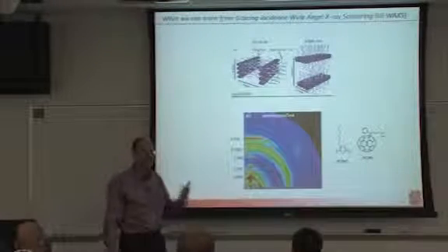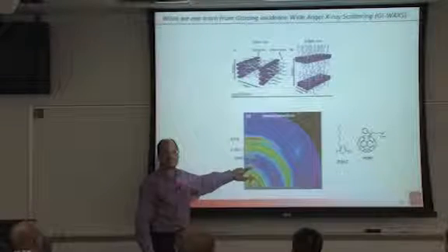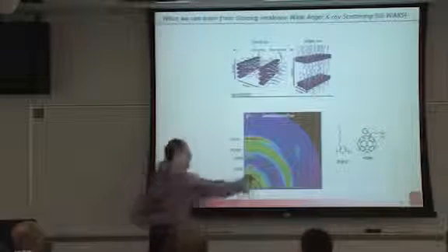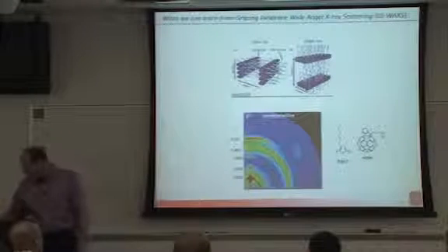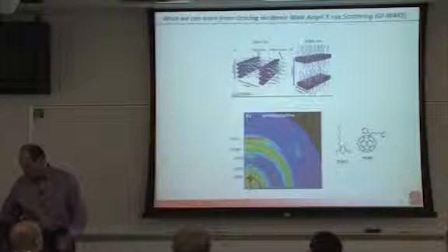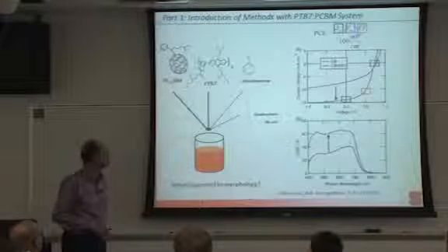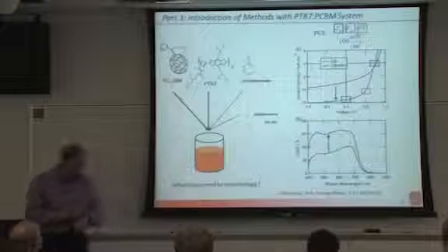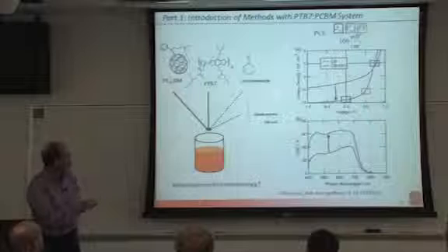Then I can see in the WAXS how well it is ordered. I can measure from the width of this what the coherence length or size scale of this ordering is, and I can see the orientation. And then with the scattering, we look at the amorphous parts, we look at all of it, and we look at other length scales. So let's go through an example here and use PTB7, which is one of the high efficiency materials. Co-dissolved in chlorobenzene with and without DIO.